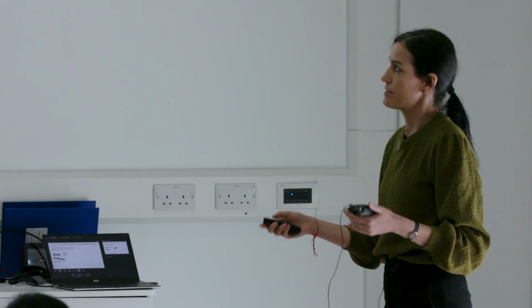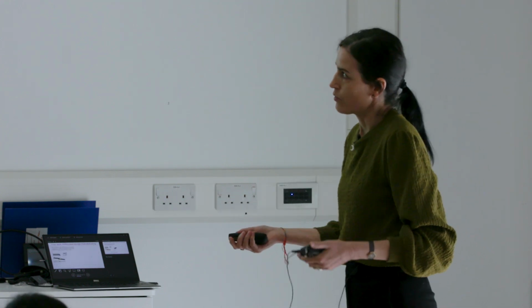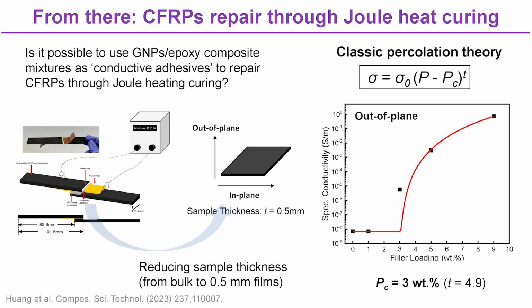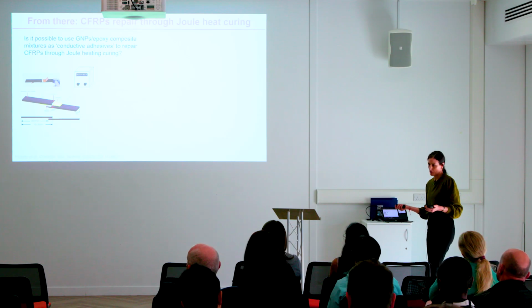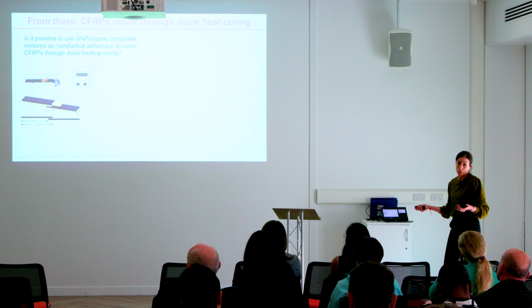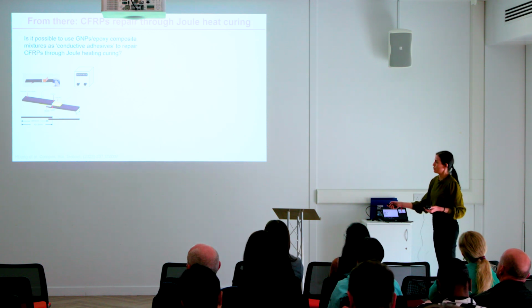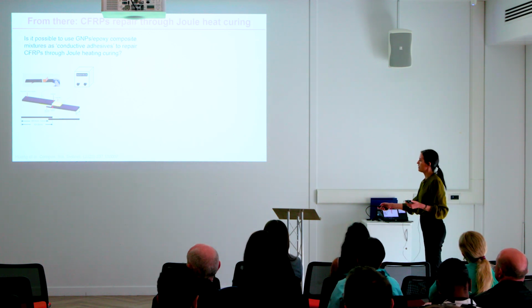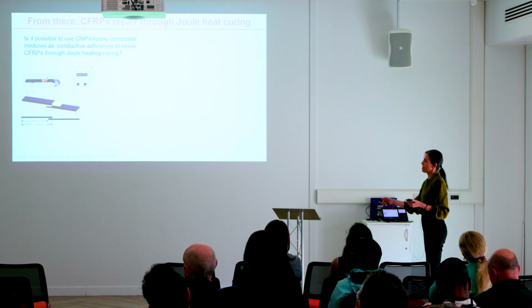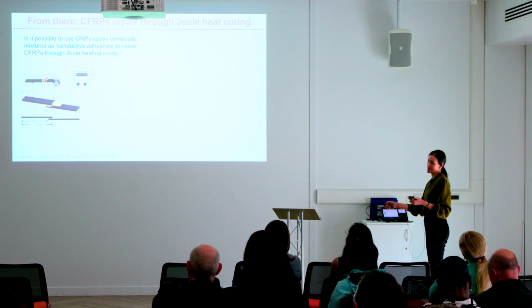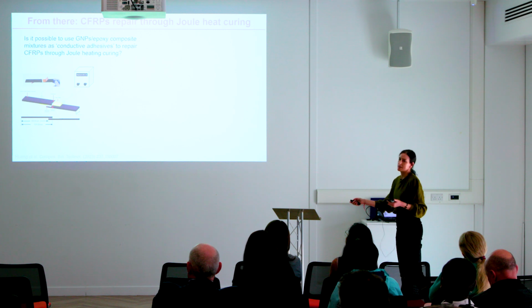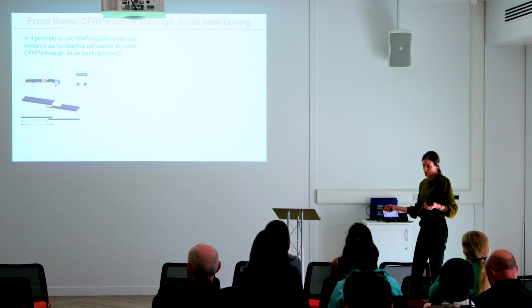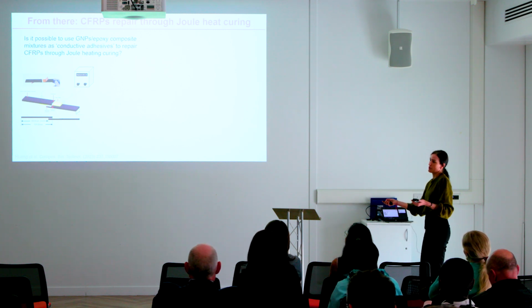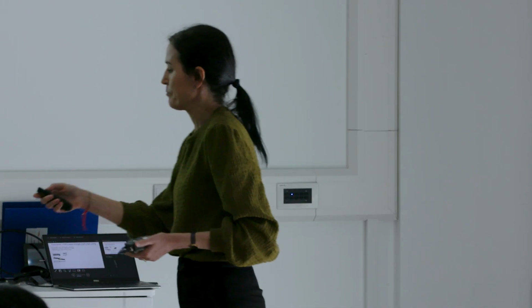So from this point, and to go one step forward, we started to wonder, would it be possible to use these electrically conductive nanocomposite mixtures as conductive adhesives to repair composites through Joule heat curing. Basically, we have here two pieces of composite. We will put a little bit of our adhesive here in between them both all throughout the bonding area. We will apply an electric current, and once the adhesive is completely cured, then we can say that the composite has been repaired or bonded together.